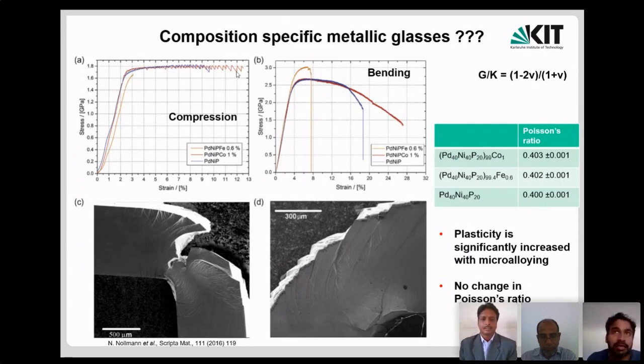I can say yes, but it's not necessarily true, because the problem is producing these glasses in bulk scale is not very easy. I haven't described how a glass is produced here, but in general, if you take a normal silicate glass, all you need to do is melt the glass and then pour it in some die, and then you get a window glass, very easy. Whereas in a metallic glass, it doesn't happen. When you pour it, you get normally crystalline material. So what they do is rapid quenching. They use some melt spinning or something where they pour the glass, or they use suction casting where they have very high cooling rates, like 10 power 6 Kelvin per second or so.